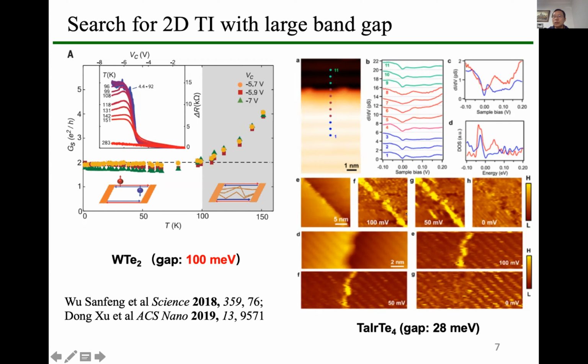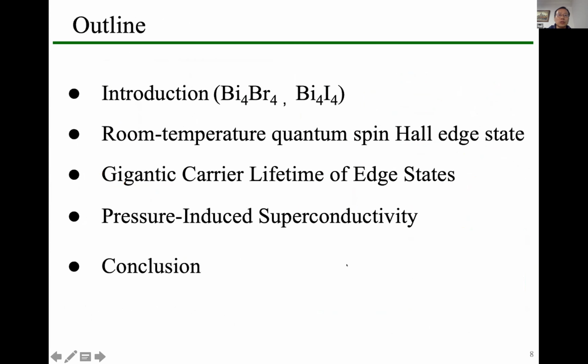In 2019, we also observed the topological edge states in this material, the tantalum iridium telluride. But this is not enough. Is this tantalum iridium telluride structurally one-dimensional or two-dimensional? This is two-dimensional. But I just want to say that this two-dimensional TI includes these new materials. But today, what I would like to tell you is this new family of quasi-one-dimensional TIs.